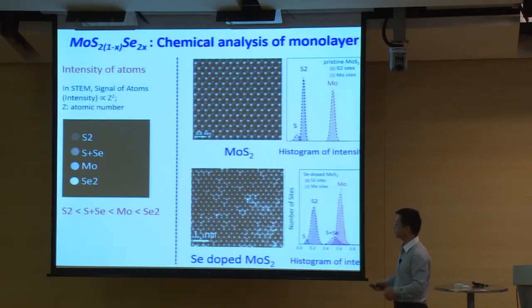Okay, maybe before I move to the TEM part, I give a very brief introduction for how to read these images. All the TEM imaging we took is using annular dark field STEM images. And for this kind of image, you will see we have different atoms, and they are either bright or dark. Actually, the intensity of each atom has a relationship with the atomic number. Briefly, in short, the heavier the atom, the higher the intensity. So this is the defect-free moly disulfide monolayer. So these bright atoms are moly, and this is sulfur.